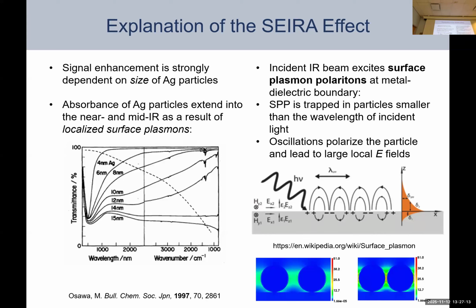of that molecule. Additionally, just the fact of chemisorption, so the molecule as it adsorbs to a surface, also dramatically polarizes the molecule. So essentially there's two different explanations here for why we're getting this really large surface enhancement. It's local electric fields, yes, but it's also chemisorption, where the molecule now attaches chemically to the surface. Okay. And this helps explain why you can still get some signal enhancement for, let's say, electrolyte or solvent molecules that are near the interface, but not chemically bound to the surface.